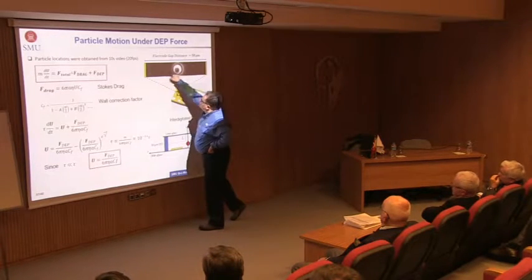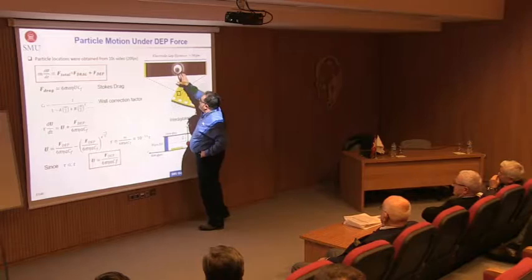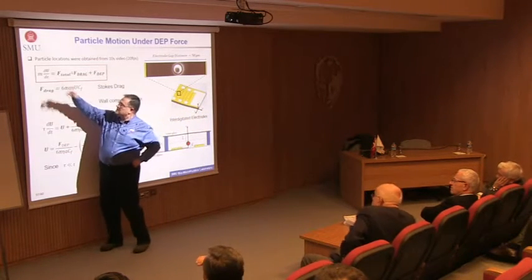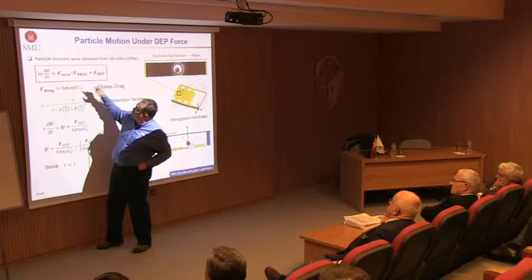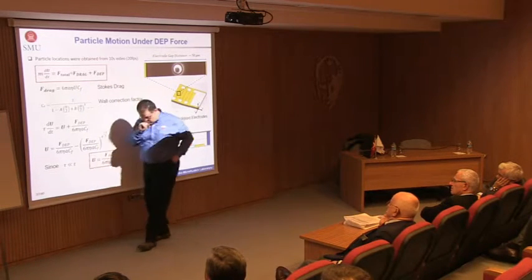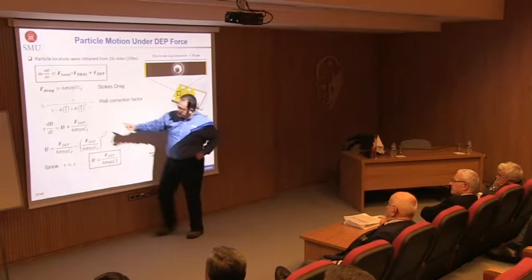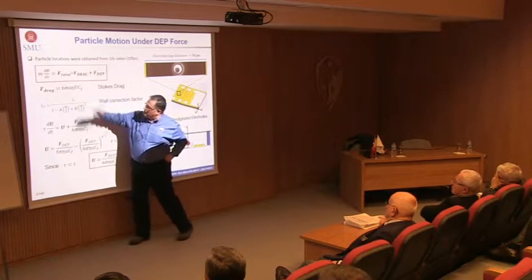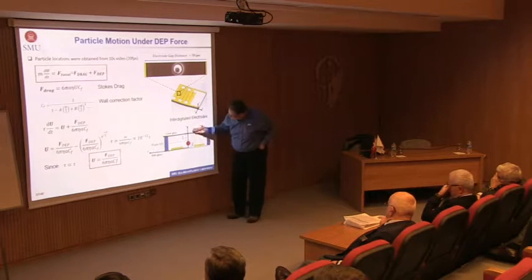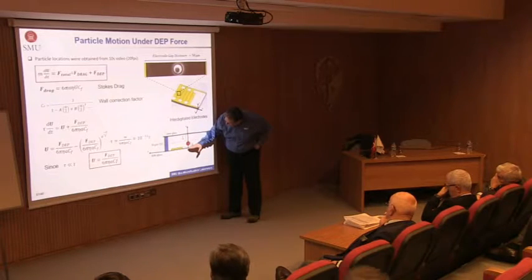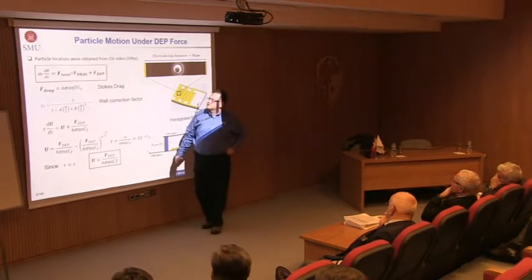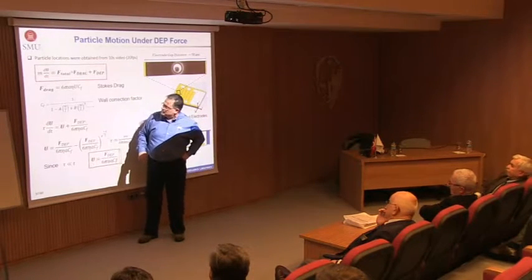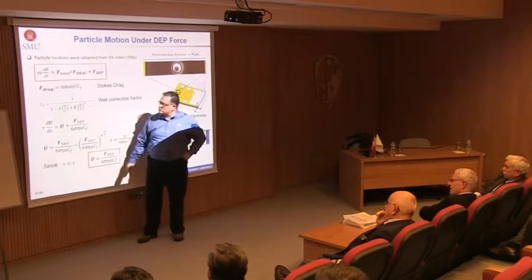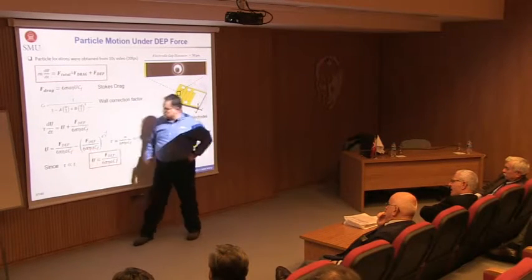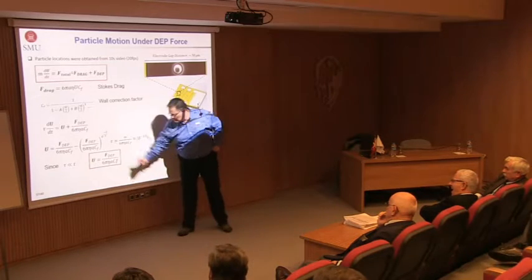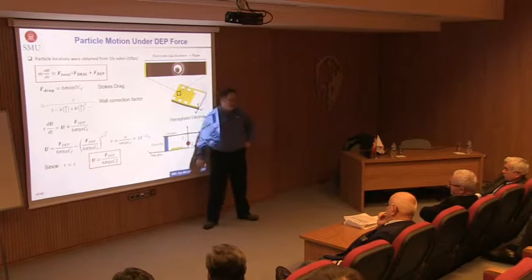So I can actually look into the motion of a cell because I'm applying an electric field, and when you look into the motion of a particle, there's mass times acceleration and the total force acting on it. Total force is made out of the drag force and the force due to the dielectrophoresis. The drag force is the typical Stokes drag, where we take care of the wall correction, because this is sandwiched in between two parallel plates. There are analytical solutions for it. You put the wall correction factor in it and so on, and you end up with solving this ordinary differential equation, and that is the solution of it. Apparently there is a characteristic time scale shown with a tau that turns out to be extremely fast.